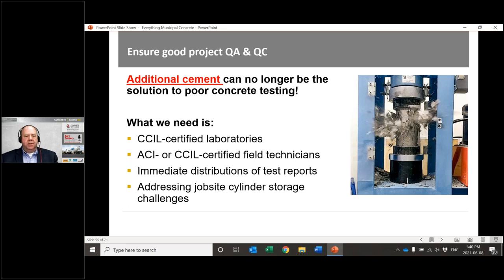So the first one is ensure proper testing. Why is testing important? Because we need to know that the evaluation of the product is going to give a fair value of what the concrete's properties actually are. So when you order 32 MPa sidewalk, we shouldn't have to send you 50 MPa concrete in order to make sure that we're not going to have failures when it's, for example, 35 degrees outside today, like it is right now. So again, one of the critical issues that all of us have to do is ensuring proper testing so that we can optimize the mix design to minimize over design.